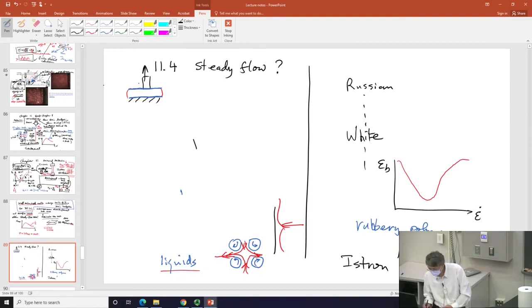So it turns out this doesn't have to be solutions. In theory, this can be melts. You just need to melt it into the molten state, and make sure the polymer adsorbs to the wall. And then there are two disks, you just grab one of the disks and try to pull. Okay? So at a later moment, this sample will look somewhat like this.